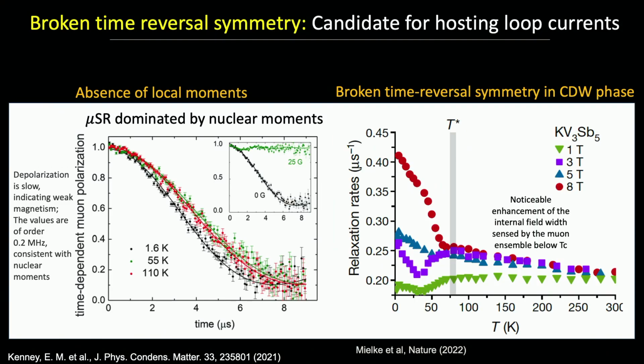They didn't have an explanation for what was going on, but it was the first indication that there might be broken time reversal symmetry. The second is that mu-SR in the presence of a magnetic field shows an enhancement of the relaxation rate below the CDW transition. Okay, well, in this, I misspoke. The CDW transition is somewhere around, I thought it was around 100 Kelvin. In any case, there's an increase in the relaxation rate in mu-SR, and this increase indicates, again, that time reversal symmetry is broken.